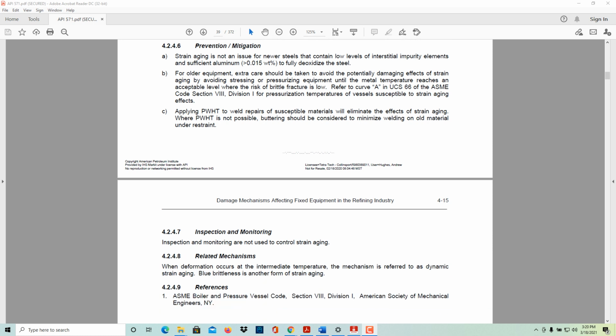Prevention and mitigation. Strain aging is not an issue for newer steels that contain low levels of interstitial impurity elements and sufficient aluminum, 0.015% by weight or greater, to fully deoxidize the steel.